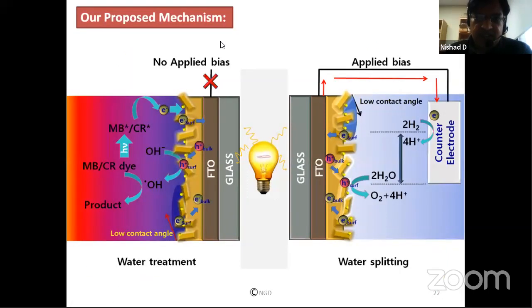So this is what our dual utility device is all about. This is what we have proposed in the mechanism, utilizing the same structures of bismuth vanadate, which is having very highly active facets for oxidative and reductive reactions. One can use this cell for water splitting, where we are applying an external bias and also the light to separate the electrons, and we can achieve the oxygen evolution, as well as the splitting of hydrogen. And not only that, the same structure, if inputted with some dyes, we can actually degrade the dyes, but now there is no external bias.